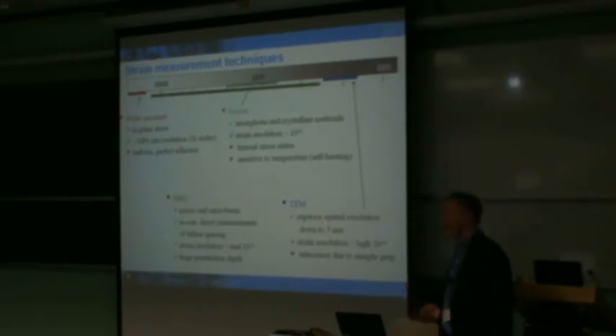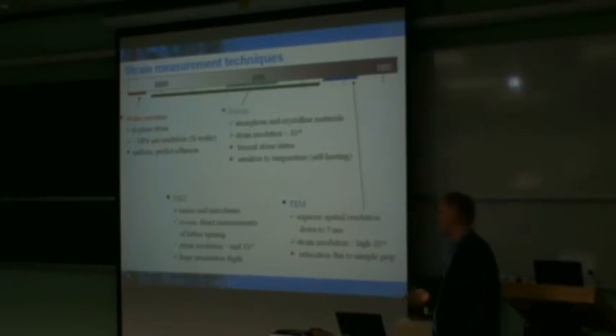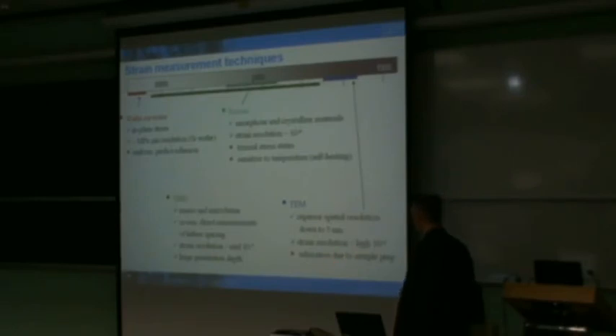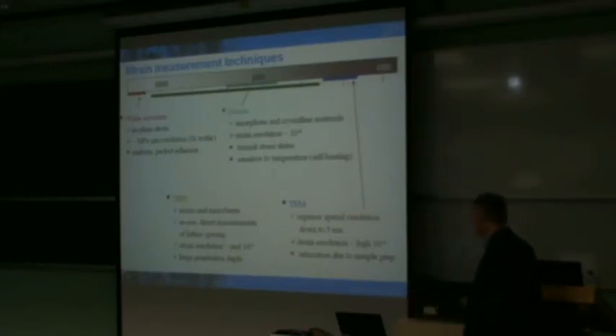The workhorse right now for looking at devices is transmission electron microscopy. Basically there is no competition in terms of spatial resolution. It runs from about 20 nanometers down to 5 nanometers, and no other technique has lateral resolution that can compete with this. One of its limitations is that the strain resolution is not as good as what we can get with diffraction. Clearly, it's not possible at this point to do in situ measurements. You always have to spend a lot of time and effort preparing your sample, and as a result there's going to be elastic relaxation. But depending on the application, it might be okay to live with.